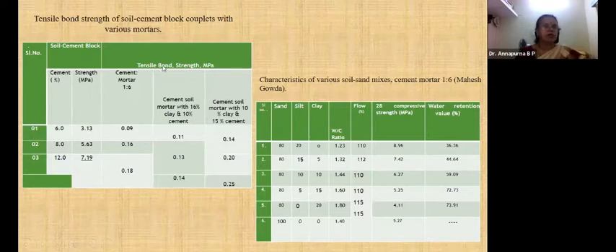Then the tensile bond strength between the mortars. For the 1:6 cement mortar, we have found it is 0.09, 0.16 and 0.18. Then for cement soil mortar with 16% clay and 10% cement, it is 0.11, 0.13, 0.14. Cement soil with 10% clay and 15% cement is 0.14. So the tensile strength increases with the presence of cement and the lesser clay content.